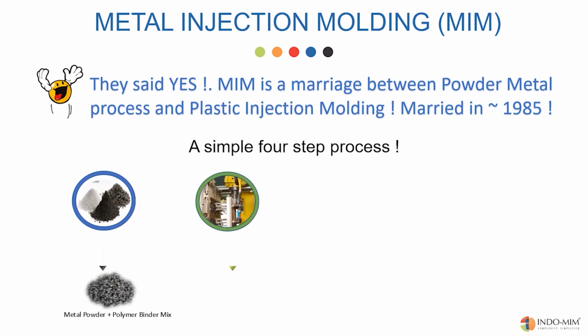Step 2. The feedstock is injection molded into complex shapes using plastic injection molding machines. During the injection molding process, the MIM feedstock is heated just enough to melt the plastic. So essentially, we inject semi-solid material into a custom-made mold. A molded shape is only a consolidation of the metal powder with the help of plastic. At this stage, the parts are called green parts. The green parts should be handled delicately to avoid damage.